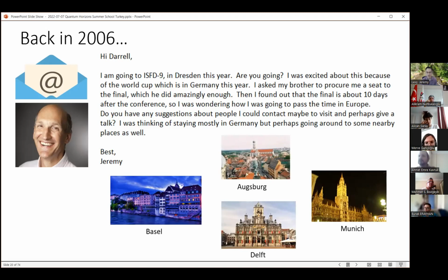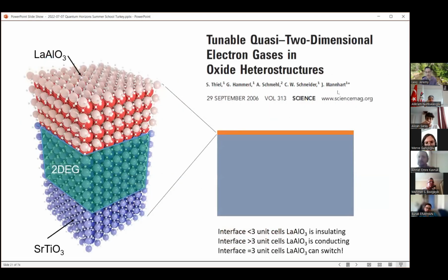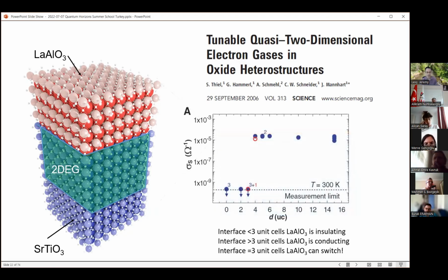One of the places that I went to was the University of Augsburg. In Augsburg, there's the group of Jochen Mannhart, and they had not published this paper yet, but they told me about the result, which was really interesting. They were looking at complex oxide heterostructures. In this case, there's a thin layer of lanthanum aluminate, which is a wide-band insulator, grown on strontium titanate. What they found was that depending on how many unit cells of lanthanum aluminate, the interface of the strontium titanate near the lanthanum aluminate would either be insulating or conducting. It was a very sharp transition. With 3 unit cells, the interface was insulating, and if you put one more, it became a conductor.